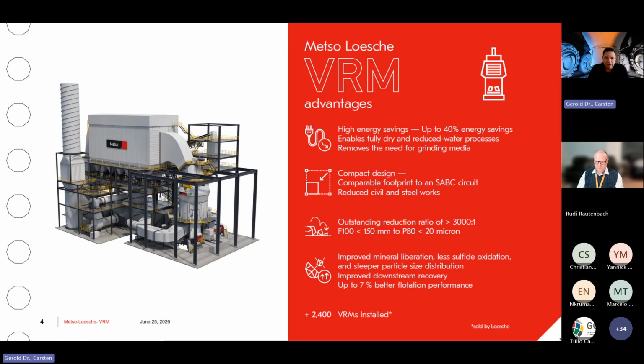The VRM, or vertical roller mill, is kind of misleading because it's really crushing and grinding. And the advantages we see are that, depending on the circuits we utilize, we can provide energy savings of up to 40%. It's a dry grinding technology, therefore it enables fully dry or reduced water processes. We don't need grinding media.